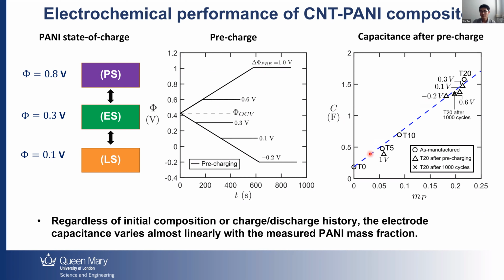After several tests, we found that regardless of the initial composition and the state of charge, the capacitance varies almost linearly with the measured PANI mass fraction, as you can see in these lines. So essentially, this type of material depends only on how much PANI is coated on the CNT. You may find that if we charge at a high voltage, for example 1 volt, there's some degradation that actually decreases the PANI mass. Therefore, the capacitance also drops.